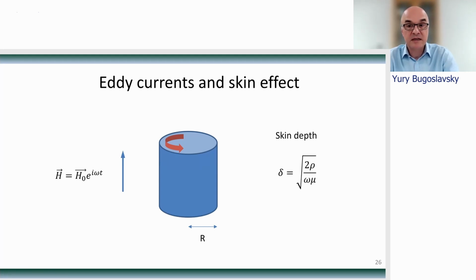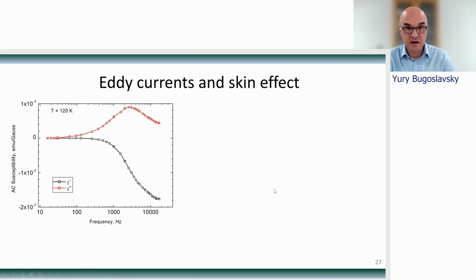Looking at the formula, we can understand that at high frequency, the skin depth goes to 0. So effectively, the circular surface currents will screen the bulk of the material from the AC magnetic field. So as an illustration, here I show you our measurement, which we made on a small copper sphere. Here we plot real and imaginary parts of susceptibility, but now not as a function of temperature, but as a function of the excitation frequency, going from about 10 or 20 hertz to about 20 kilohertz.